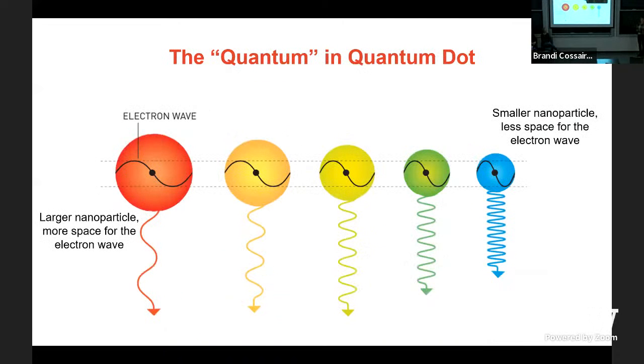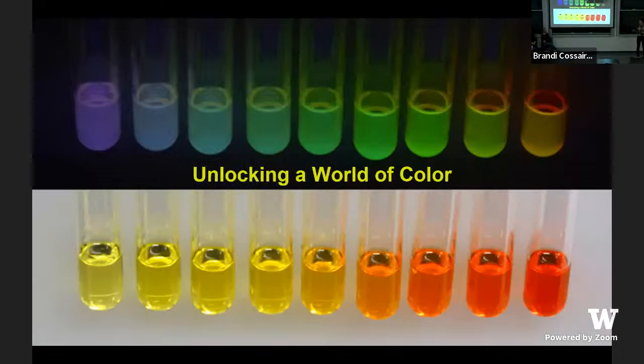And quantum confinement is how we get the quantum in our quantum dot title. So when you shrink a material down to the size of your electron wavelength, you start to run into this problem where your wavelength is now bigger than your material. So your electron wave function has to squish itself to be able to still fit in your material, forcing it to a higher energy than it wants to be at, and giving us a higher energy emission in our smaller nanoparticles. And that's how we can get pictures like this, with one material giving us emission in the blue, and also in this orangish yellow, just by changing the size of the nanoparticles.